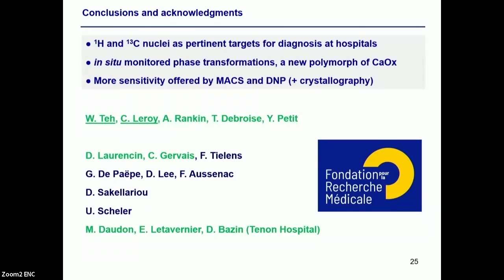Christian, very nice work. Concerning the solid state transformation, you mentioned calcium oxalate as a MOF. Can you comment on, one, the porosity, and two, is the transformation you observe purely temperature driven, or is it also pressure driven? Yeah, that's a super question. What I have in mind soon is to do experiments with variable rotor diameters in order to play with the centrifugal force. I would say that pressure should have an impact. Here, without temperature regulation, you have this evolution. If you regulate the temperature very actively, then pressure plays a role because you still have transformation, even at low temperature.